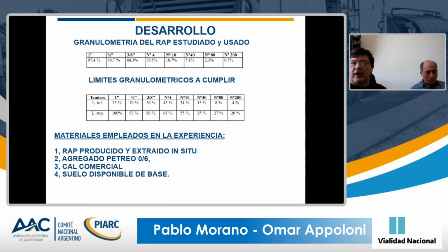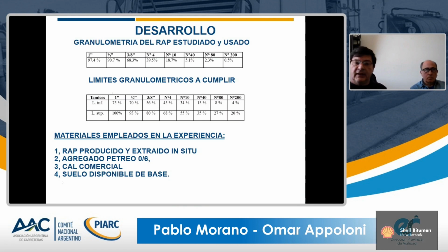The first thing was to study RAP that was aged, and it worked as inert material, as recovered material to be used in asphalt mixes. We can see the granulometric numbers. It's quite coarse, and then we have the granulometric curve at the bottom to do granular stabilization for this type of material. So 100% of RAP was corrected with stone fines, commercial lime and soil from the base.